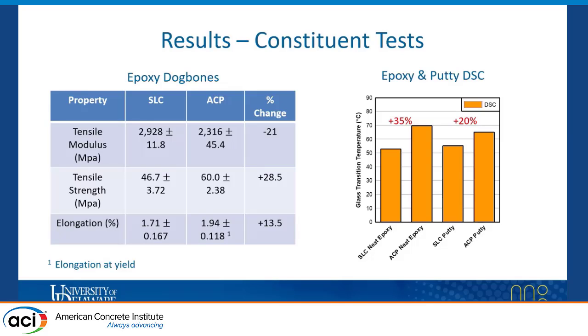SLC and ACP dog bones demonstrated different behavior. The SLC dog bones initially demonstrated linear elastic behavior. However, following conditioning, they demonstrated an elastoplastic behavior. In addition to that, tensile modulus also decreased. However, the tensile strength and the elongation of the dog bones increased following conditioning.